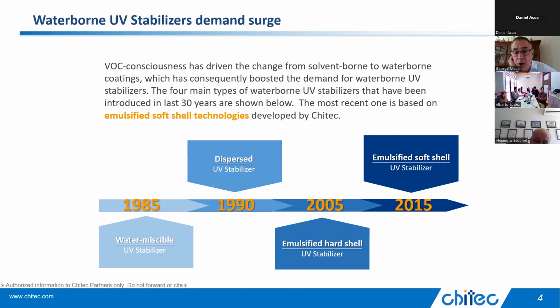And then around 2005, there were some hard shell materials that came out, which were benzotriazoles, but they brought in a lot of emulsifier, a lot of carrier material, and they weren't necessarily easy to incorporate into the paint or stay stable in the paint. So there were compromises there, although clearly the material had a little better performance than the earlier dispersed stabilizers. And then around 2015, Chitec came up with what we call a soft shell UV stabilizer, which is taking a well-known benzotriazole and figuring out how to emulsify it in a highly concentrated form. So it just brings in a little bit of emulsifier, and it has been working quite well. It's extremely compatible. It's stable within the coatings, and we'll show you a little bit more about that now.